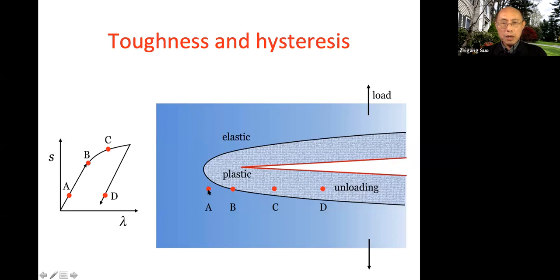So if you look at a material particle way ahead of the crack, this part is still elastic. Near the boundary between plastic and elastic, you have yielding here, right? And in the wake after the crack, because the stress is released, if you are way behind the crack tip, you start to unload. As the crack moves forward, each material particle goes through this ABCD, this hysteresis, and dissipates energy. Now you dissipate energy over a macroscopic scale, not an atomic scale. That's why toughness is so high for metals. So that's the picture for metal.